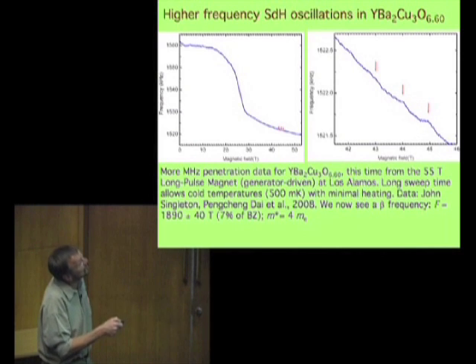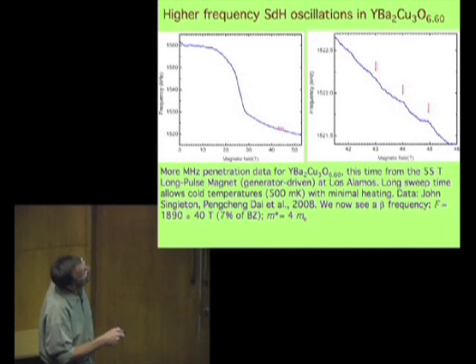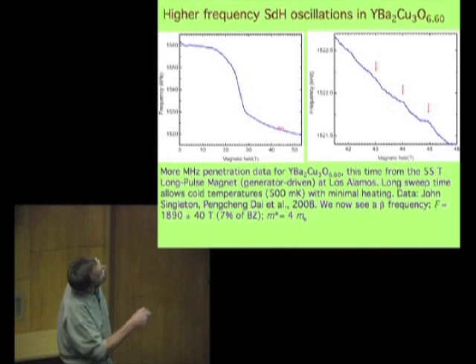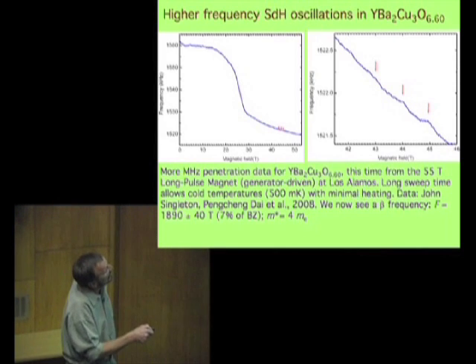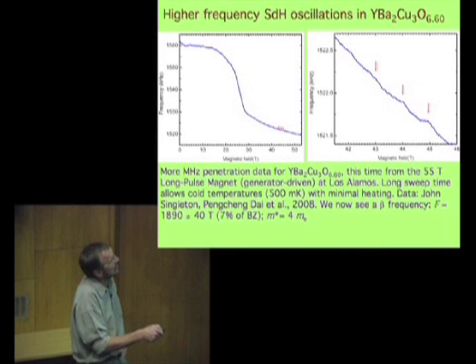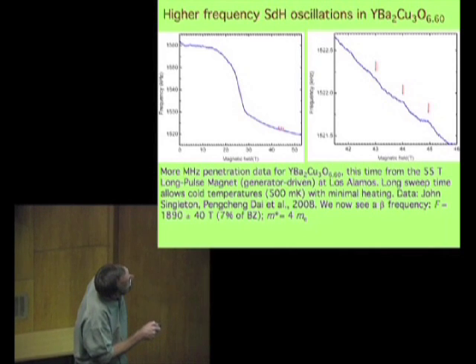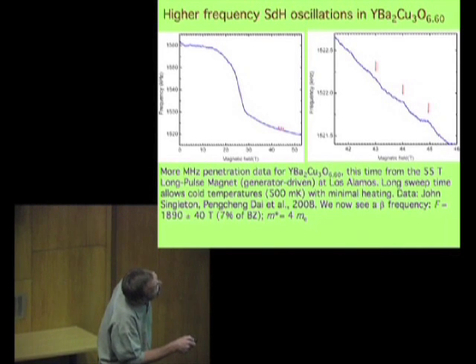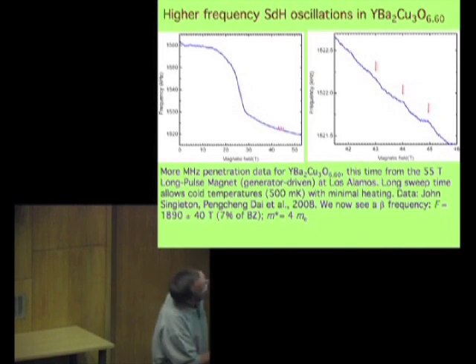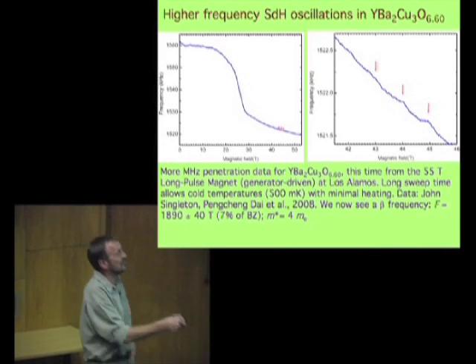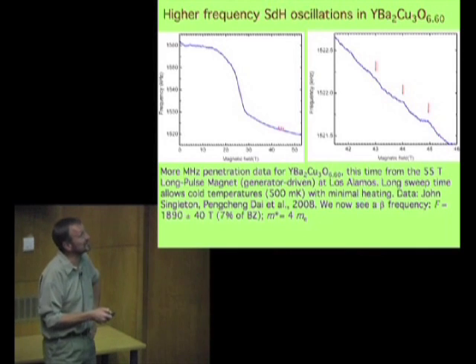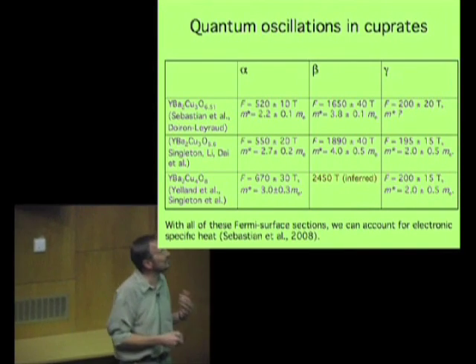This is the 1, 2, 3, 6.6. These are just taking raw data. This is the sweep of a different pulse magnet, this time the 55 Tesla long pulse magnet at Los Alamos user facility. These little arrows here correspond to the arrows that you can see when we blow this section up. And I think you can see that there is an oscillation there, and it's of a frequency of about 1,890 Tesla. So it's about time for a summary.